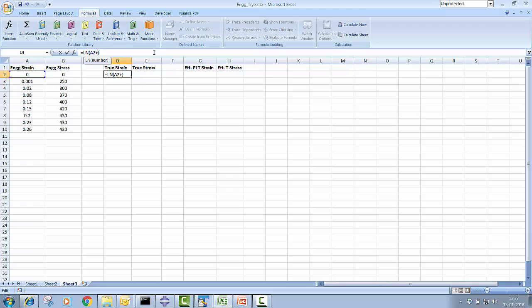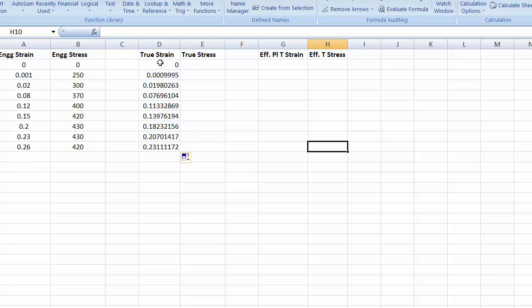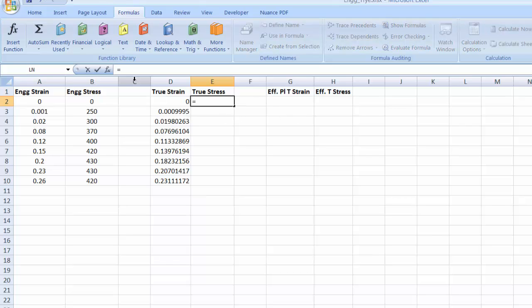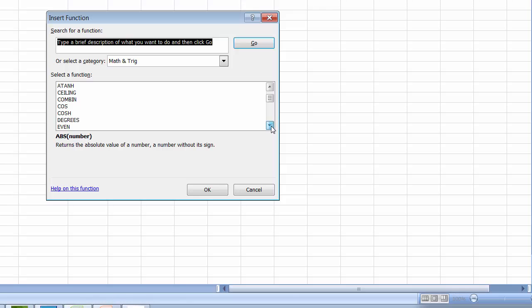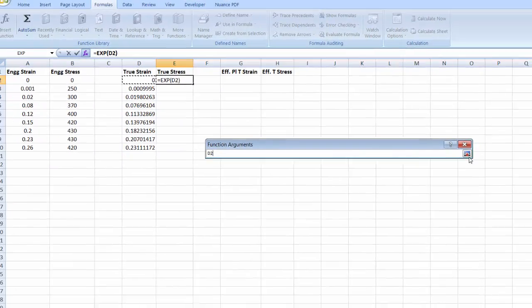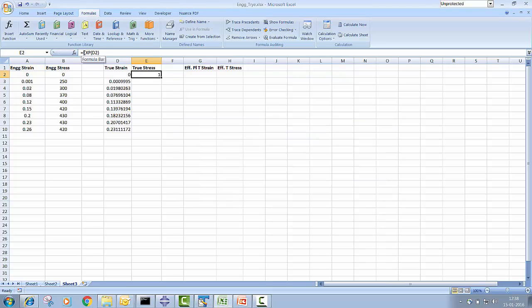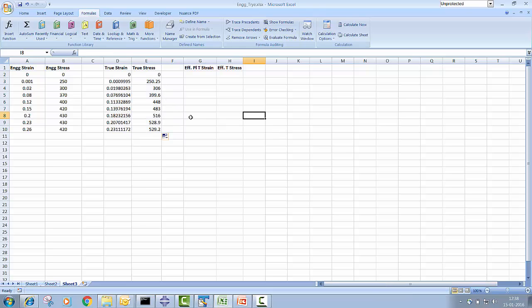In the formula, you need to add plus one — so it becomes LN(engineering strain + 1). Simply drag this down and the true strain values are ready. Now we move to true stress. We use the exponential function — EXP of true strain — and then multiply by the engineering stress value.